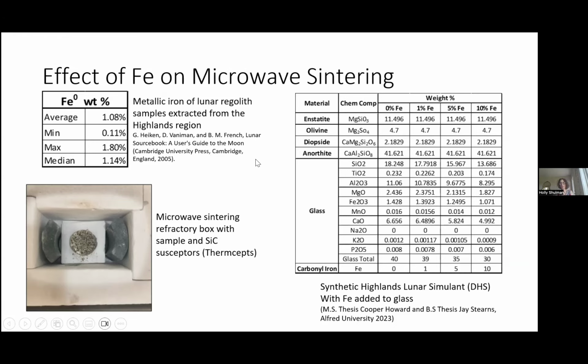So what we did with our synthetic lunar simulant, which I call DHS, is we added iron to the glass component. And we used it through a carbonyl iron. And we know that in the end, we did have iron because we did X-ray diffraction, and we clearly showed that we kept those peaks. So we were very careful not to let oxygen attack it at any stage in that processing.